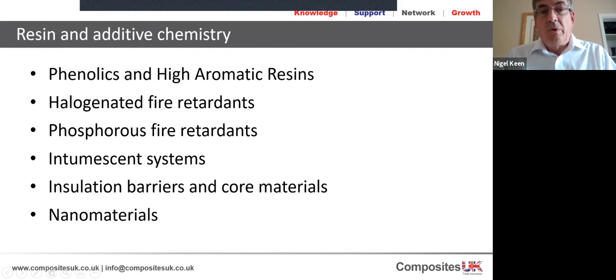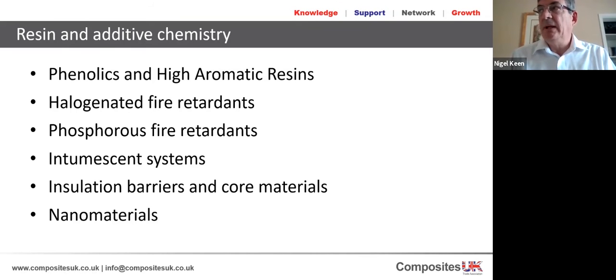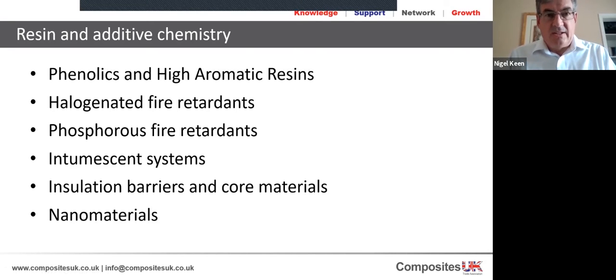Phosphorus fire retardants can work very similarly. You tend to need a little bit more of them to carry out the same effects. So again, the phosphoric acids and things like that can actually do very well in suppressing flame chemistry. They're slightly more benign, generally speaking, in the environment than halogens. Still a little bit corrosive sometimes, and certainly halogenated products like hydrogen bromide, hydrogen chloride, they're all acids, so they're not great when you're talking about the fire products potentially having a corrosive effect or a toxic effect. So phosphorus is sort of a replacement for halogen, somewhat less effective, but somewhat more environmentally benign, and finds increasing use.